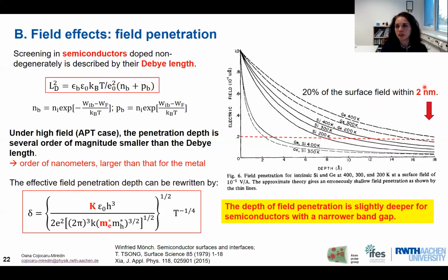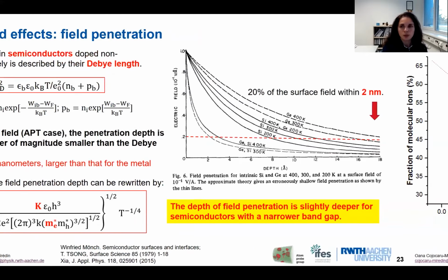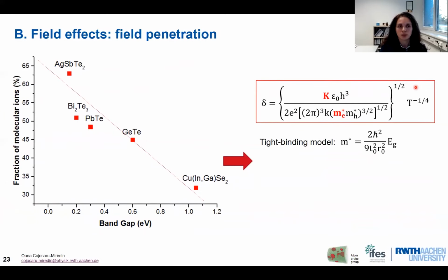This is definitely much higher compared with what we have seen for the metals. And if we want to see now a certain correlation between the fraction of molecular ions and the band gap, since we work in our lab with many chalcogenide materials, I have drawn here the fraction of molecular ions for several chalcogenide materials based upon their band gap. And we see here copper indium gallium diselenide, a photovoltaic material as I have presented before, with a band gap of about 1.04 or 1.05.